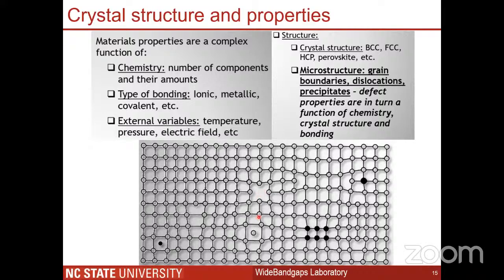Then you can have a defect called an interstitial defect, where you have the constituent atom incorporated in the lattice, but it is not at the exact lattice site. So you can see that it incorporates in between these 4 atoms. And this can be termed an interstitial defect. We can also have the foreign atom occupying this site. And we can have a cluster of these foreign atoms coming together to form a defect complex. So all of these defects can be termed zero-dimensional defects because they are only one point.